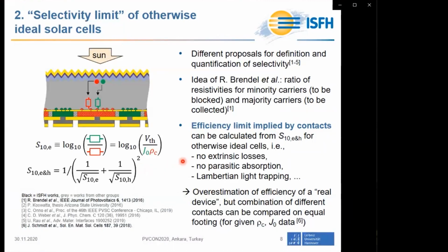No other extrinsic losses are taken into account, no parasitic absorption in these contacts is considered, and perfect Lambertian light trapping is assumed. Of course, this approach will yield an overestimation of the efficiency of a real device, but it nevertheless allows for a comparison of different combinations of contacts on equal footing for a given experimentally determined set of rho C and J naught data.